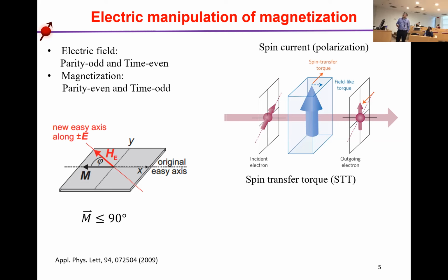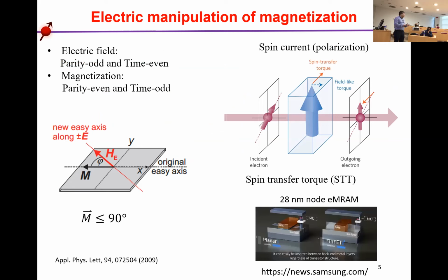Spin transfer torque is where an electric current passes through a magnetization, which we call the ferromagnetic layer, and will generate a spin current. This spin current, when it passes through another ferromagnetic layer, will exert a field-like torque or anti-damping torque, and then switch the magnetization. So here, the spin current polarization has a similar symmetry to the magnetization, which is parity even and time reversal odd. As I mentioned, it is not only Avalanche, a US-based company, and UMC. Samsung and GlobalFoundries had commercialized this STT-MRAM about 2 years ago, I think. Samsung's is based on the 28 nanometer node eMRAM, and GlobalFoundries on the 22 nanometer node.